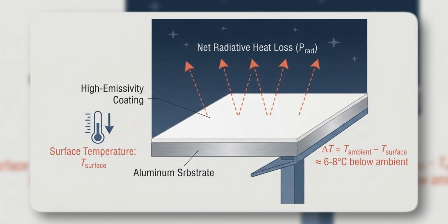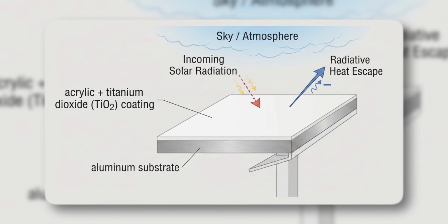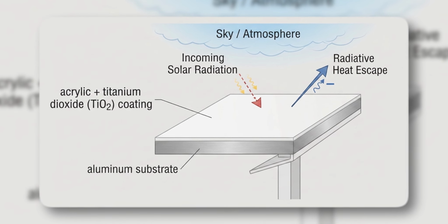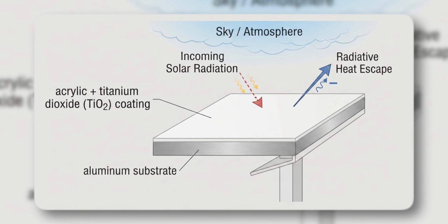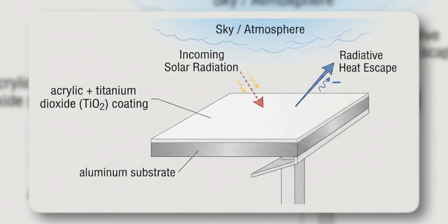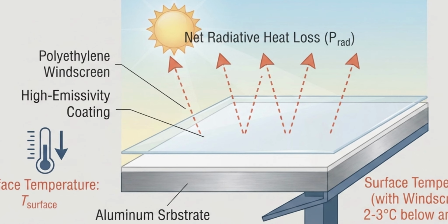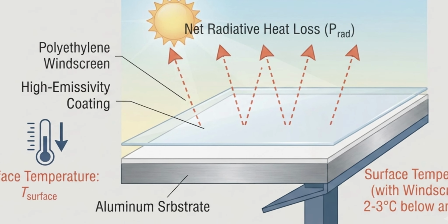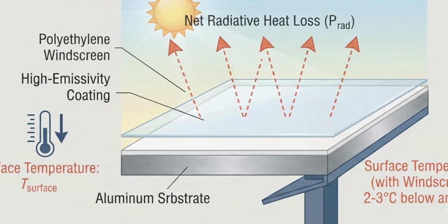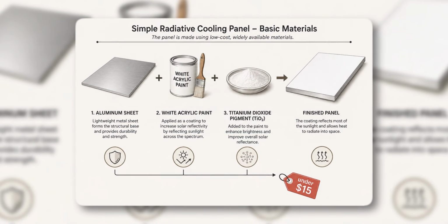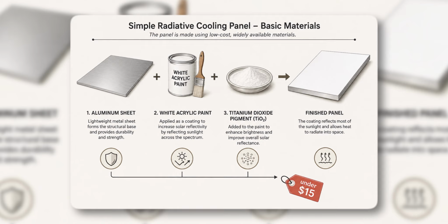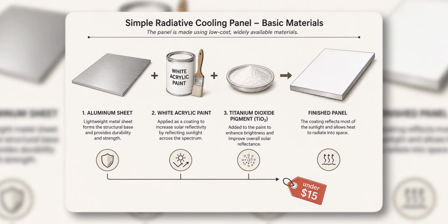Separately, researchers in Mendoza, Argentina, tested a much simpler version. Aluminum sheet coated with white acrylic paint loaded with titanium dioxide, a coating anyone can mix themselves. Their panels hit 6 to 8 degrees Celsius below ambient on clear nights, and still manage 2 to 3 degrees below ambient during the day behind a basic polyethylene windscreen. Total material cost per panel, under $15.